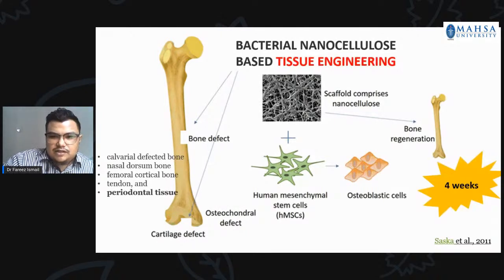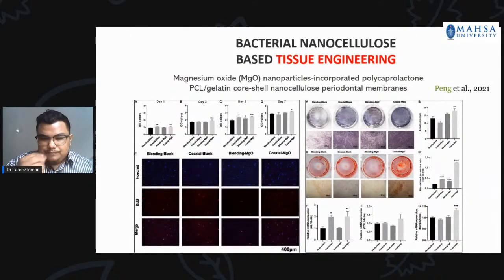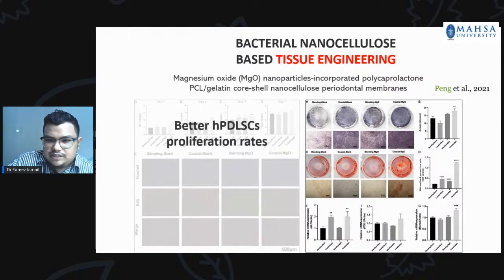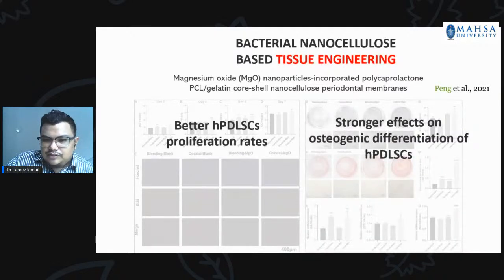And for my fellow colleague in the faculty of dentistry, putting this one good example that was just recently published in March, where they are incorporating magnesium oxide nanoparticles in the polycaprolactone/gelatin core-shell nanocellulose for periodontal membranes. So, based on the result, it shows that this composite or membranes made of the nanocellulose show better human periodontal ligament stem cell proliferation rates. And one of the results shows that it has a stronger effect on the osteogenic differentiation of this human periodontal ligament stem cell, HPDLSC.